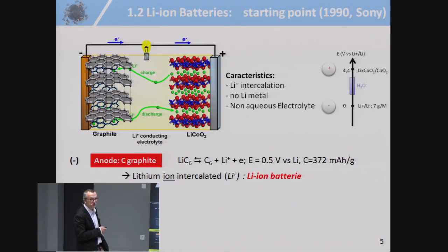But here, in this material, lithium is lithium ion. Okay, this is not lithium metal. This is a carbon which is going to see a decrease of oxidation state. So this is what we call the lithium ion intercalated graphite, and this is where the lithium ion battery name comes from. So this redox reaction, the intercalation of lithium ion into the graphite here, is achieved at very low voltage versus lithium, 0.5, and gives a capacity of 372 milliampere hour per gram. So this is today the negative electrode that you have in your cell phones, in your laptops, whatever you want.